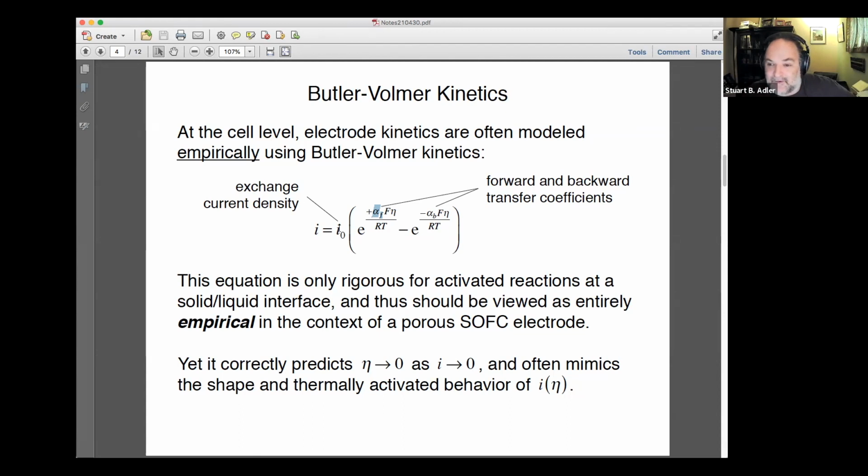What it basically represents is how much the transition state energy shifts around when you create a driving force for the reaction to take place. This is affected by temperature because it's an activated process, meaning we have some probability of an event happening and going over a barrier, just like in chemical kinetics. When we make the temperature higher, the rates tend to get higher because we can get over that barrier more easily due to thermal fluctuations.